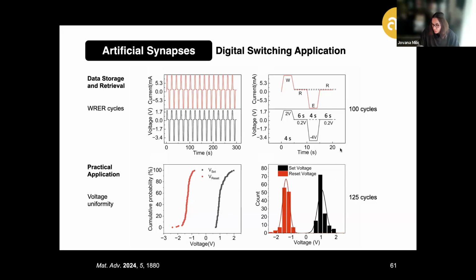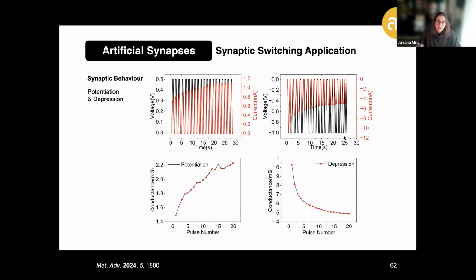Importantly, this is illustrated for both the bromide and iodide counterions, but the difference that you have seen at the beginning, with these more abrupt or gradual changes that depend on the migration of the corresponding ions, were also reflected in the differences in their behavior under these voltage pulses.